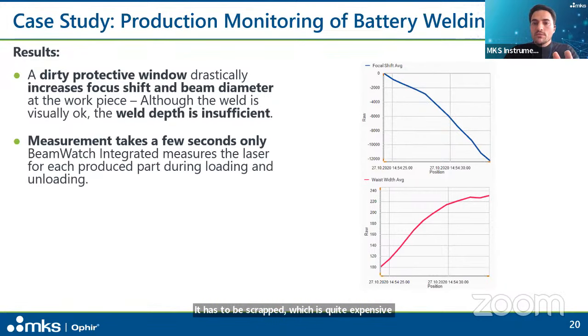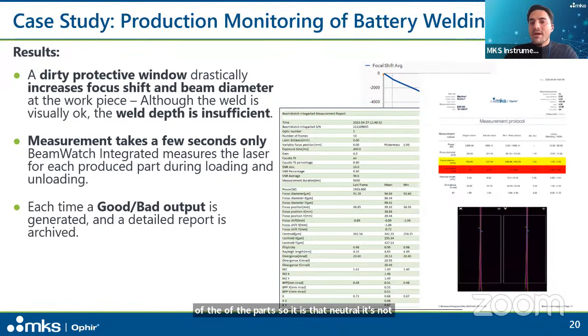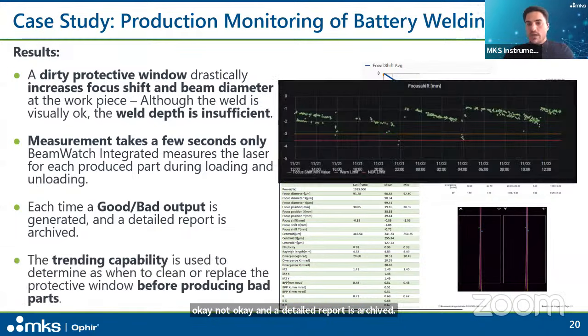BeamWatch Integrated measures the laser after each produced part. The measurement takes only a few seconds and is performed during loading and unloading of the part, so it is takt neutral. It's not taking production time. Each time a pass-fail output is generated, so you can define the parameters for the pass-fail, and then you have an okay, not okay, and a detailed report is archived. Finally, the ability to recognize a trend is used for predictive maintenance, and the protective window is cleaned or replaced before producing bad parts.